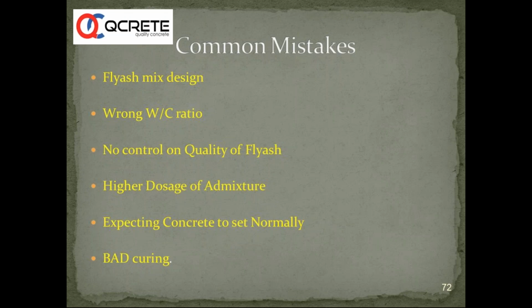If you want to get the same strength, let us say you are using 320 kgs, you want to get the same strength of 320 kg OPC, you need to increase the total cementitious. On the other hand, if you don't want that much strength, which is given by 320 kg OPC, then in 28 days or early stages, you can just replace by 10%, 20%, 25%, whatever it is. So we should remove the concept that the 320 kg OPC mix is equal to 320 kg OPC plus fly ash mix, at the same water cement ratio.